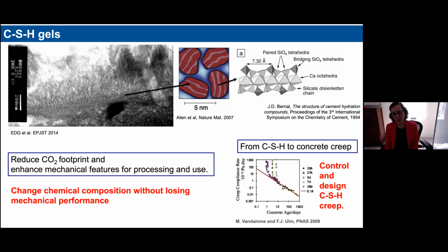Well, at the very small scale, this material, as I said, precipitates as nanoparticles. These nanoparticles have a layered structure that is very similar to the structure of a rare mineral called tobermorite, as was recognized already by Bernal several years ago. The nanoparticles then form amorphous structures, which then aggregate into this type of gel that has a very wide pore distribution.